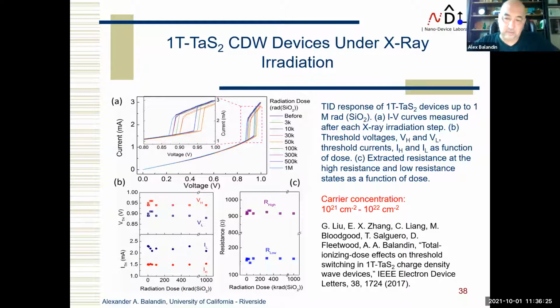And the reason for that is the following. Some people claim that graphene FETs or 2D FETs are radiation hard. Not really, because your charge neutrality point will go crazy under any radiation. The argument that radiation just goes through doesn't really work well. But in this particular case, this is metal. It's the first case where we are switching between two metallic states, with high carrier concentration.